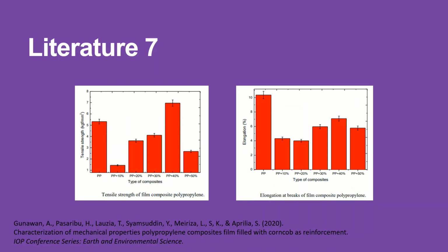A similar trend of elongation at break was observed in a study conducted by Gunawan et al. in 2020, where corncobs were used as a reinforcing material in the polypropylene matrix. The researchers also utilized a universal testing machine to study the tensile strength and elongation at break of the composites. Their study has revealed that the elongation at break of the composites decreased with increased filler loading. Tensile strength, on the other hand, was found to increase as filler loading increased.